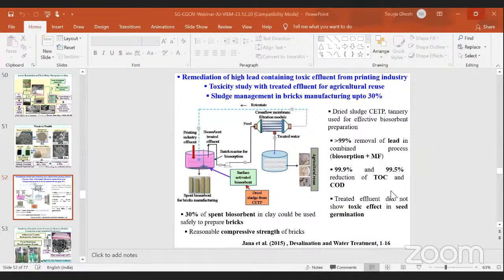Another work is the treatment of high lead containing toxic effluent produced from the printing industry. So this effluent contains a high percentage of toxic heavy metal, that is lead. So we had used our sludge-derived biosorbent in arresting the heavy metals, adsorbing the heavy metals. Then after adsorption, the effluent was treated by the ceramic microfiltration process, and this is the treated water produced. So the applicability of the treated water was studied on the seed germination process and plant growth.